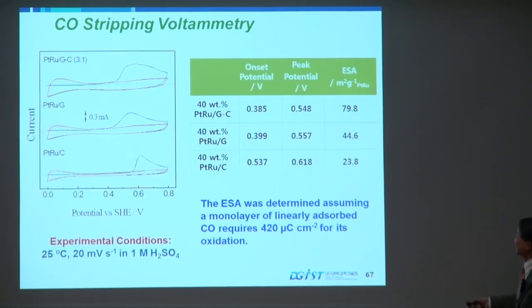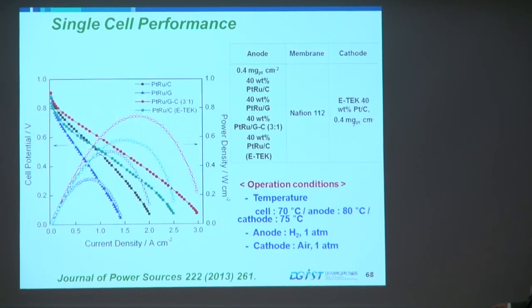And same as this, onset potential, CO stripping, electrochemical surface area: graphene with Vulcan carbon has the highest electrochemical surface area compared to platinum ruthenium on graphene and platinum ruthenium on carbon. So the surface area improves very significantly, and also the onset potential occurs earlier than the other two cases.